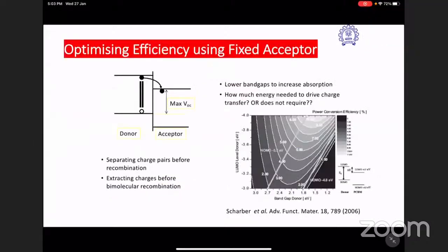Okay, so the idea was that optimized efficiency using organic solar cells was kept by fixing the fullerene, that buckyball, and that kept the field for 15 years on hold, and we could improve the efficiency from 1% to 10%. That's what this simulation paper also told.